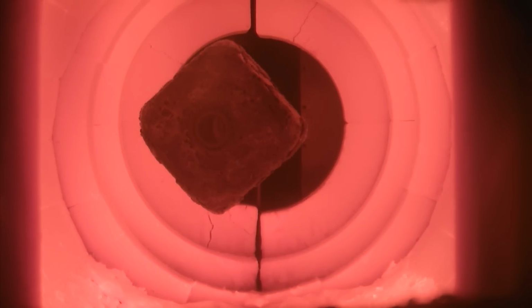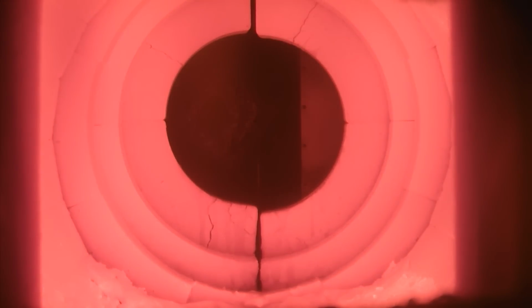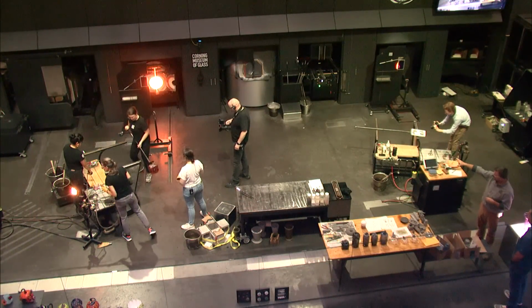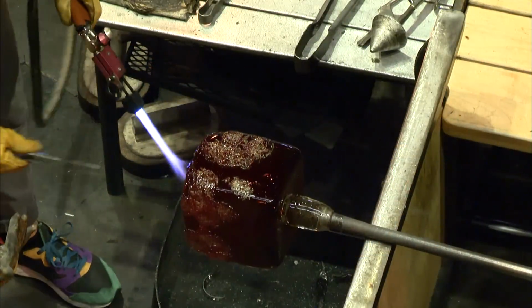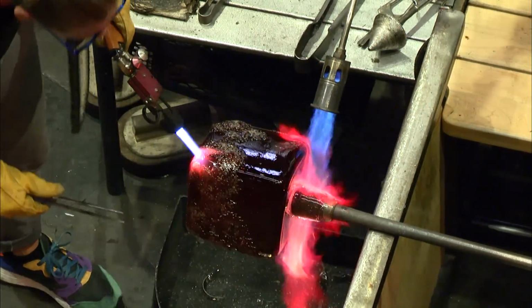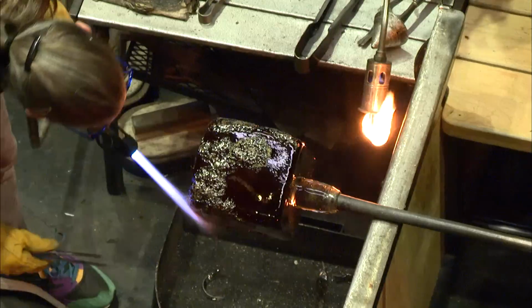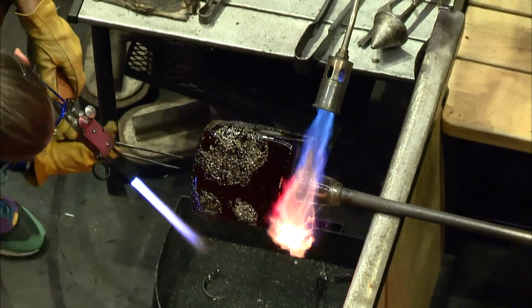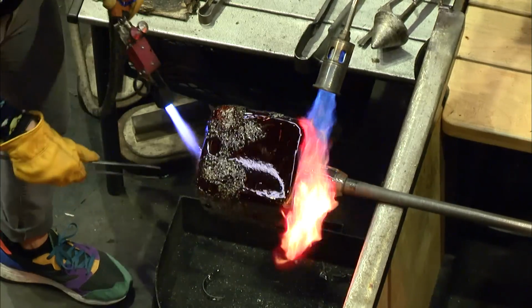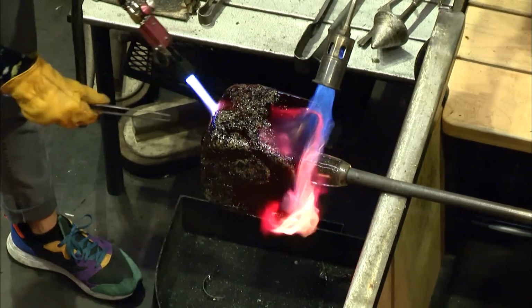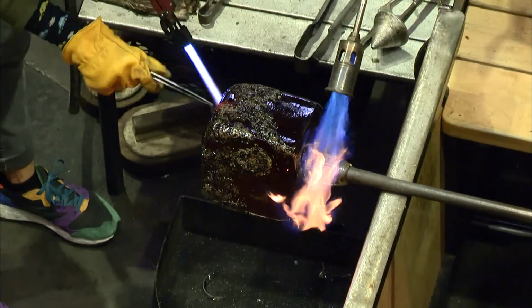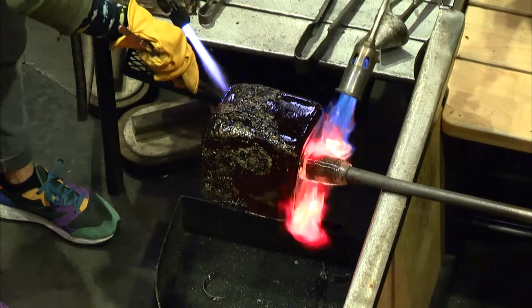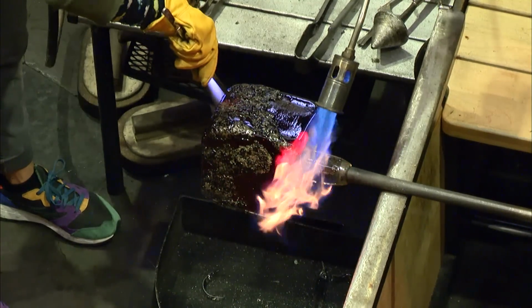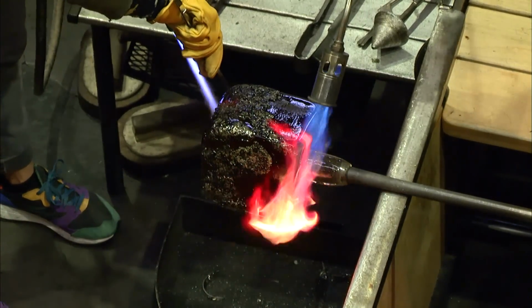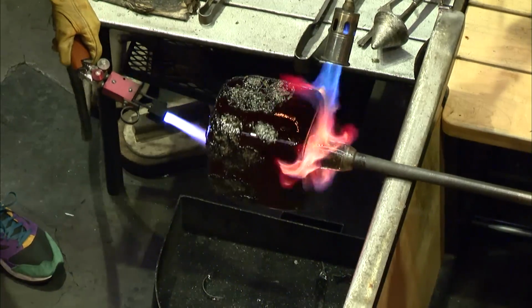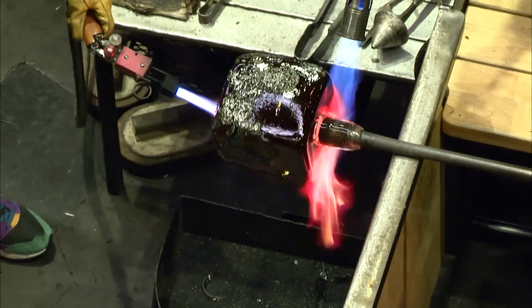So the furnace that we have here is on 24 hours a day, 7 days a week. The crucible inside will last us probably 8 years, maybe 6 to 8 years if we're lucky. It's amazing that 2,000 years ago they could do this stuff. It is amazing. I mean, 2,000 years ago, they were doing the same stuff. They were melting glass with wood fire. They maybe didn't have the sophisticated materials that we make our crucibles out of, alumina, zirconia, silica, but they were probably using a clay that was very hard and durable, and maybe their crucibles only lasted a couple days.